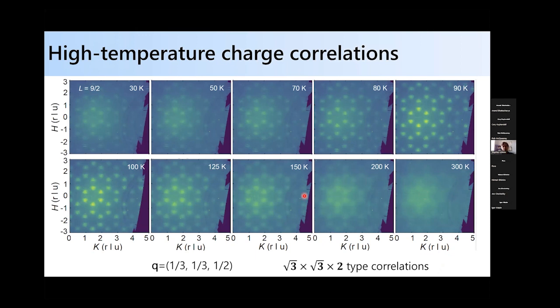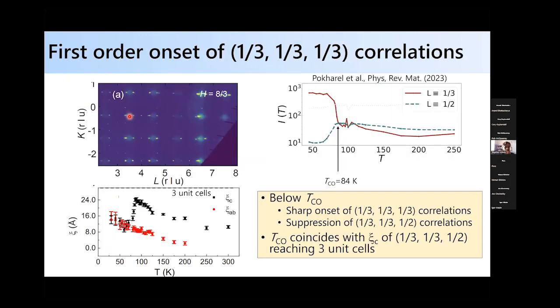You can see there are these diffuse charge correlations that grow and then strengthen and reach a maximum intensity right at the onset of charge order. And then they dampen as you cool below that. Okay, so these are short-range correlations at the DFT-predicted structure, which is also naively potentially a frustrated lattice.